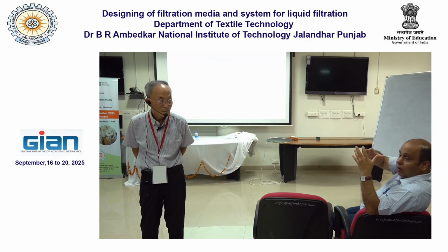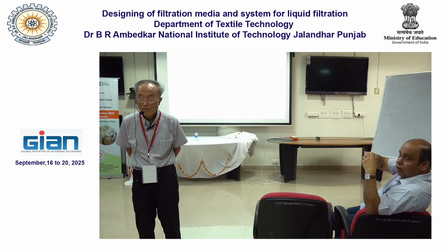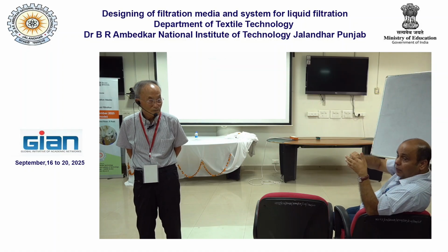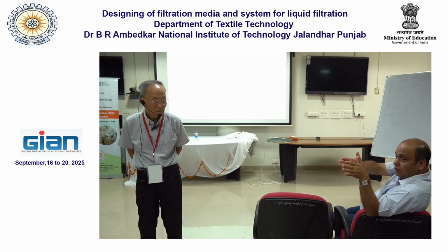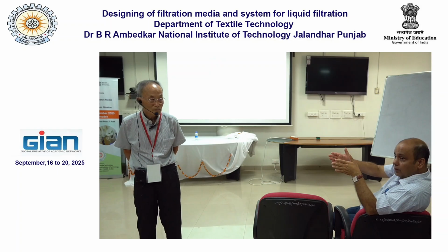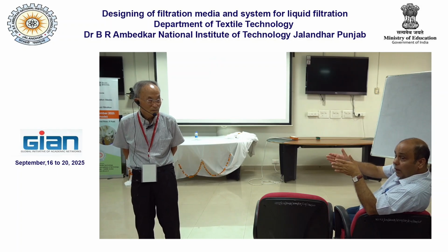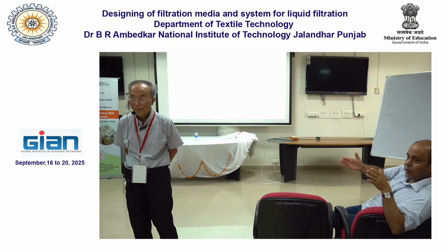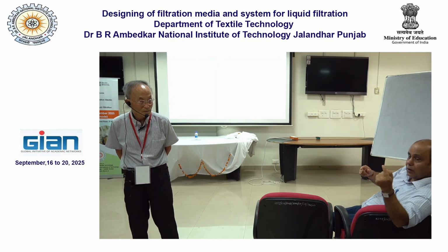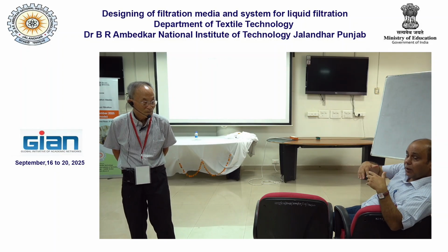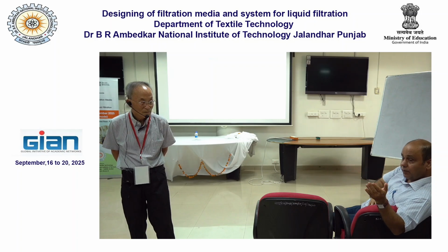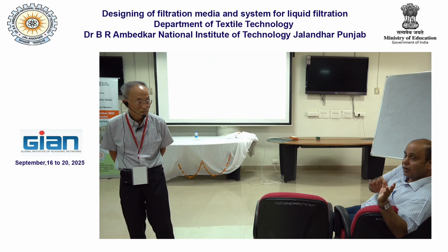It is not giving you the resistance that way. Normally, the surface area applicability is up to a certain extent. But if you are going for the nano range, it is not so applicable. Are you getting my point? Normally, if you go from coarse fiber to relatively fine fiber, you have a larger surface area. Larger surface area gives higher resistance. Higher resistance means higher pressure difference.